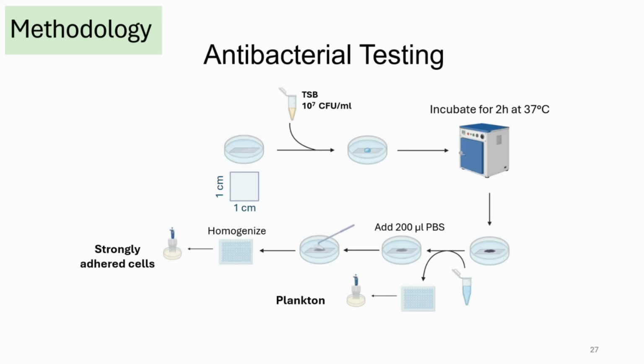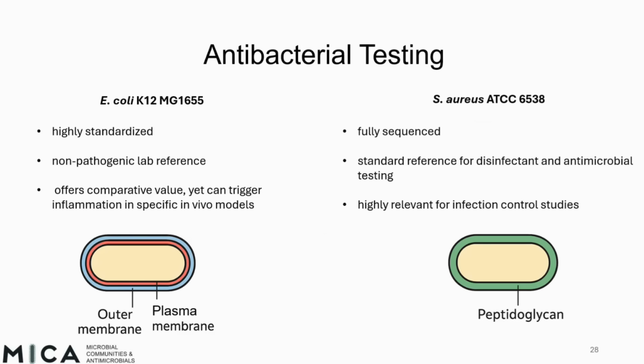We used this protocol for this assessment, in which on a 1 by 1 centimeter coated coupon, we add a droplet of bacterial culture diluted in TSB. We incubate for 2 hours at 37 degrees. We plate out the planktonic cells. Then we scrape, homogenize, and plate out strongly adhered cells. We tested our coatings against two pathogens, E. coli, because it is a highly standardized, non-pathogenic lab reference. It offers comparative value, and Staphylococcus aureus, because it is also a standard reference for disinfectant and antimicrobial testing, and it is highly relevant for infection and control studies.